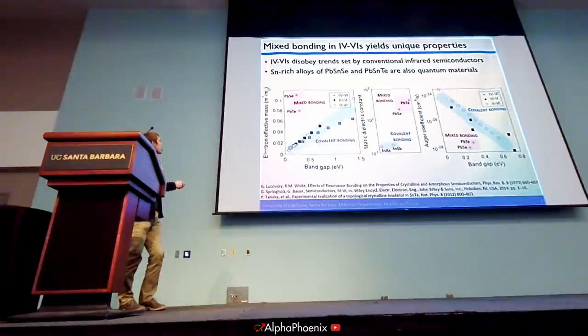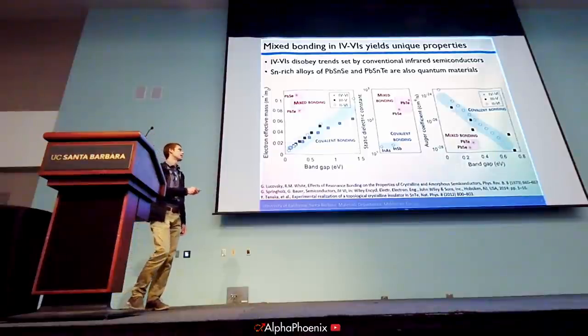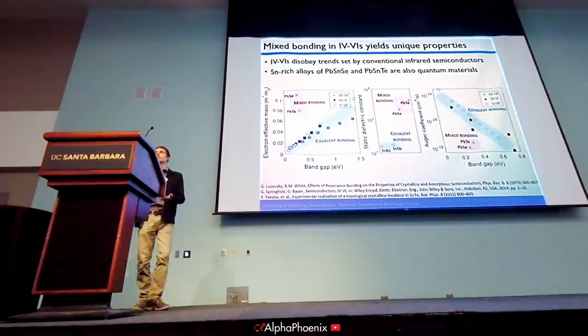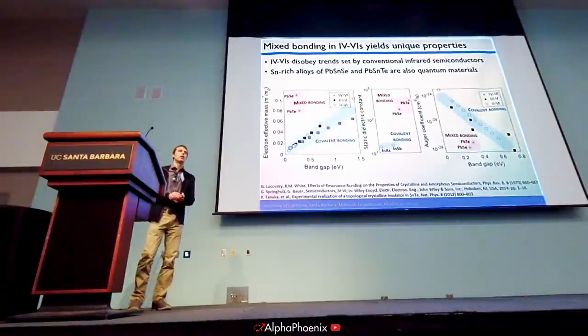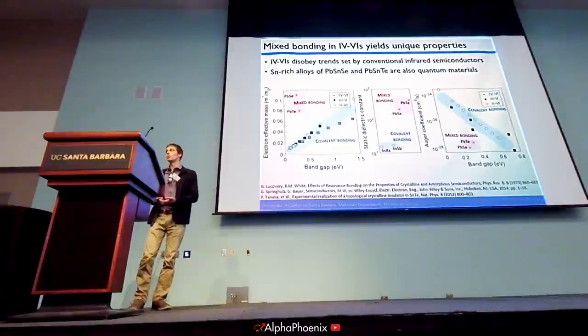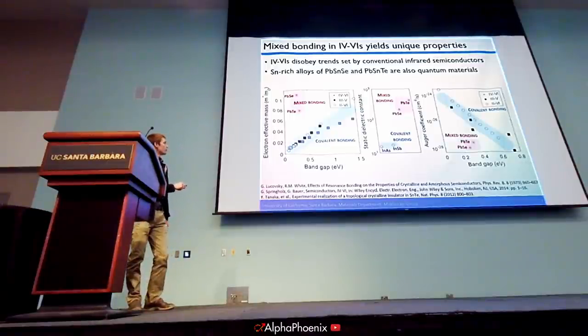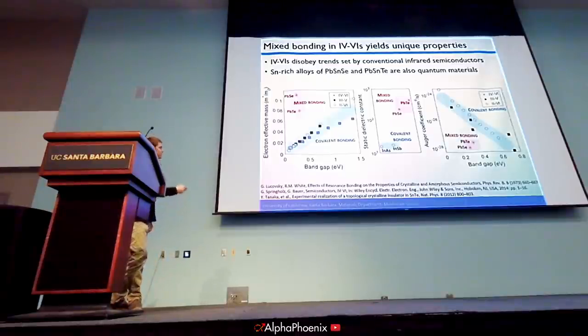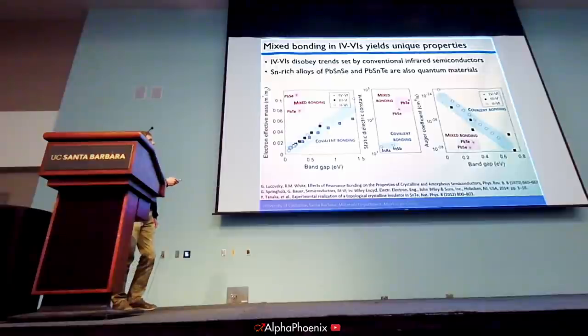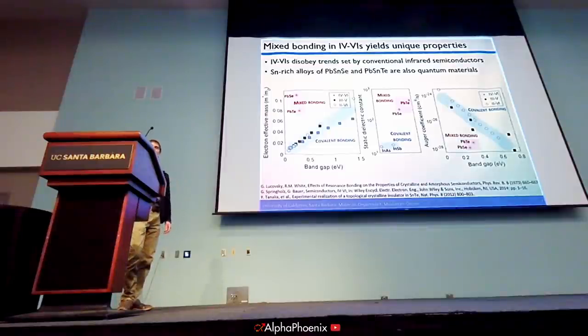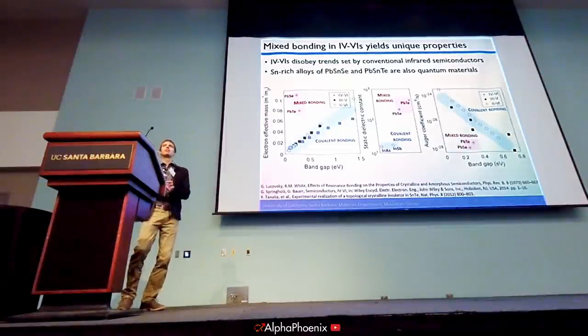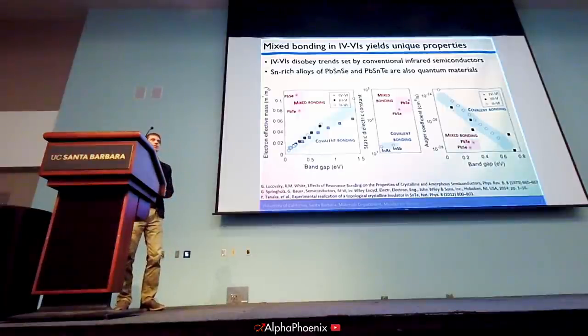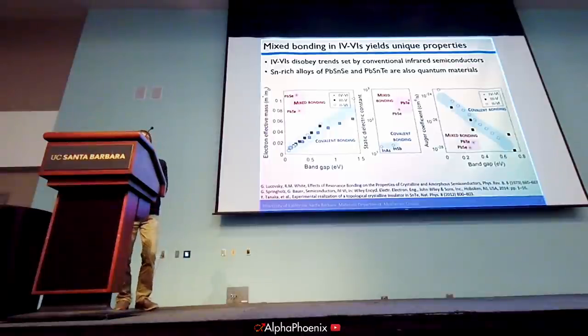I'm not going to explain all of these properties, but electron effective mass, static dielectric constant, and Auger recombination are properties we look at to see how resilient to defects and how efficient at emitting light a semiconductor will be. All of the covalently bonded semiconductors form pretty significant trends, and the 4-6s just sort of ignore those trends and do their own thing — and in this case, they're going in good directions when they break those trends. Even if they weren't, the fact that they don't obey the rules of classically studied semiconductors makes them very interesting and worth studying.